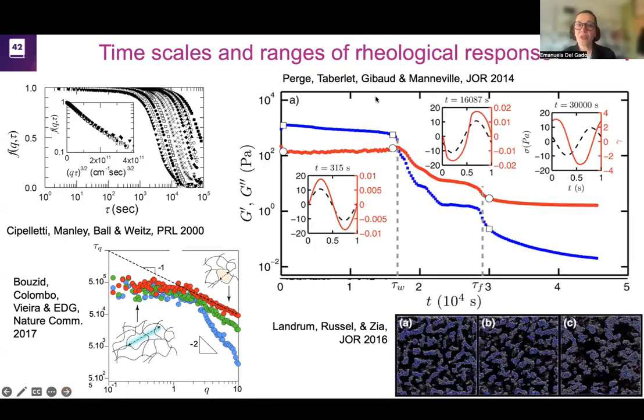And so this is another beautiful experiment by the group of Sébastien Manneville, where they imposed a cyclic varying stress to induce the fluidization of the gel. And then they were studying how, as a function of the number of cycles, so as a function of time, the viscoelastic response of the gel changes, and this is what is plotted: G prime and G double prime.